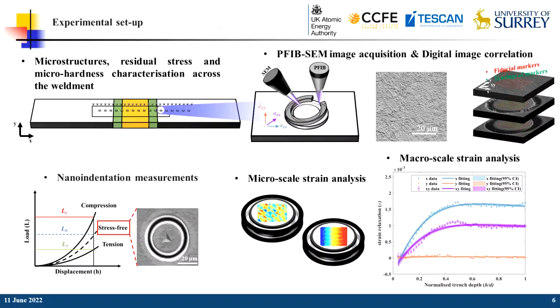We then applied the nanoindentation method for the residual stress evaluation. The ring milled by the PFIB provides the residual stress-free reference areas to calculate the residual stress at other locations. The PFIB-DIC method provides the location-dependent stress ratio, which is K, to transfer the equal biaxial residual stress to non-equal biaxial. This is to overcome the main limitation of the nanoindentation residual stress method, and also provides a cross-validation for both the PFIB-DIC method and the nanoindentation method.